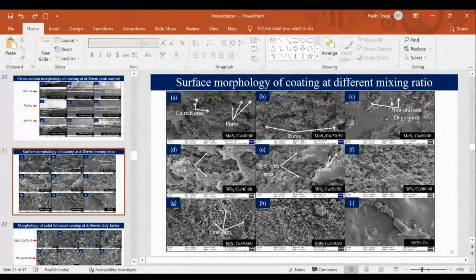Why? Because MoS2 is not completely conductive. MoS2 is a semi-conductive material. So when we increase the percentage higher than a certain level, a non-uniform deposition takes place, because it becomes difficult for the current to go through the electrode and deposit the whole amount. So the non-uniform deposition takes place.